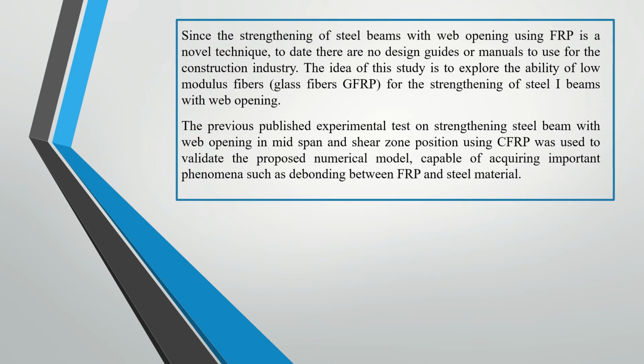Since the strengthening of steel beams with web openings using FRP is a novel technique, today there is no guidance or manual to use. The idea of this study is to explore the ability of low-modulus fiber GFRP for the strengthening of steel I-beams with web openings. The previously published experimental test on strengthening steel beams using CFRP was used to validate the proposed numerical model, capable of capturing important phenomena such as debonding between FRP and steel.